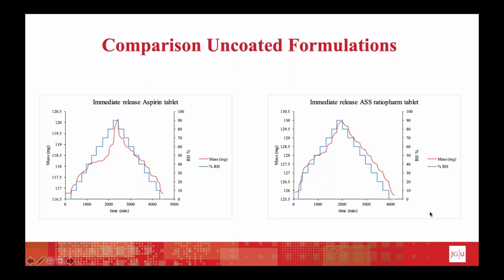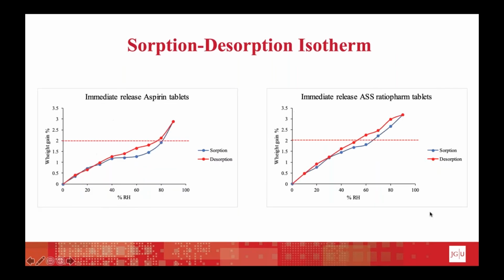From these plots, we can now take the percent weight gain at equilibrium at every relative humidity stage and plot the sorption and desorption isotherms afterwards, when we plot the weight gain against the percent relative humidity. And according to the European Pharmacopoeia in chapter 5.11, we can now classify our material or product as hygroscopic or non-hygroscopic.